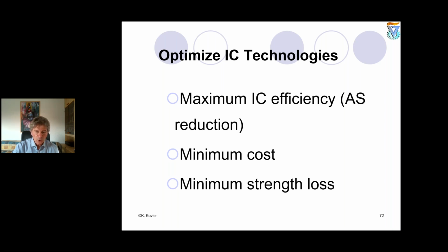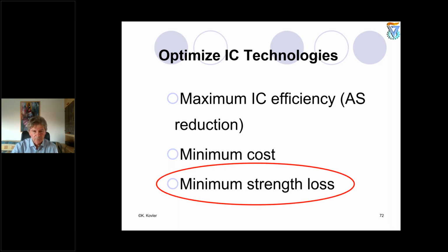But fortunately, we have a trade-off. We have improved hydration rate. We have a higher degree of hydration. We are recruiting more cement for cement hydration. And then it easily compensates, if we calculate precisely the amount of the material, take into account the water absorption and other properties, this strength loss can be easily compensated.